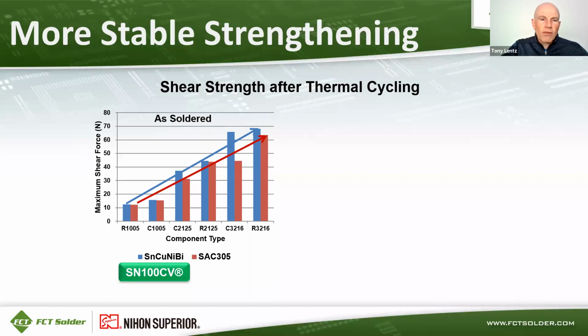Here's shear strength as soldered for SN100CV versus SAC 305. SAC 305 are the red bars for different component types. And you can see as the component types increase in size from left to right, shear strength goes up, which is expected. But the tin, copper, nickel, bismuth solder has higher shear strength overall than SAC 305 in this test, but they both increase with increasing component size.